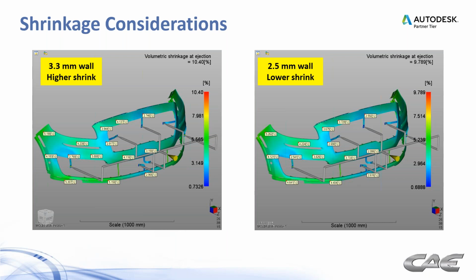Here's the fascia again, and you can see with the 3.3 millimeter wall, we have higher shrinkage numbers. These are volumetric shrinkage, not linear shrinkage, which you would cut steel to. And then when we reduce to a 2.5 millimeter wall, you can see that these shrinkage numbers come down. So in many situations here, not everywhere, and some of that's because of how the filling pattern plays out, but by and large, the shrinkage is reduced when you reduce your wall thickness.